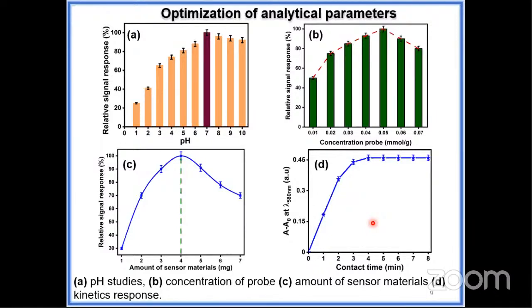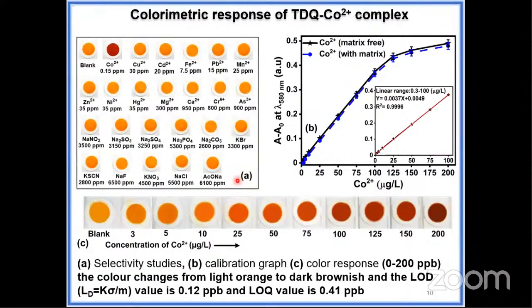Also, we investigated the properties of the material through kinetic response. It's showing a response within 3 minutes. After that, we also investigated the influence of other cations and anions. We found that the material shows excellent activity towards detecting cobalt 2+ ion with an apparent color response. After that, we also investigated various concentrations of the metal ion. As you can see here, from 0 ppb to 200 ppb, it shows a color change from light orange to dark brownish color, which confirms that even at very low concentration we can detect the metal ion.